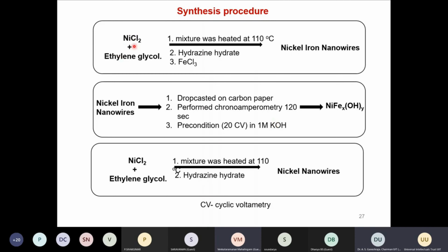What we have done, briefly, the synthesis is quite simple. You take nickel chloride with ethylene glycol, which is a structure directing agent, and we mixed this at 110 degrees centigrade with hydrazine hydrate in the presence of iron chloride. What we get is the nickel iron nanowires, which I will show the images of soon. Then to activate these nanowires, we drop cast them on the carbon paper and perform chronoamperometry. That is, we apply potential for a very short time, 120 seconds, 20 CV cycles, to get the nickel iron oxide hydroxides deposited, which have better catalytic activity compared to the metal nanowires alone.